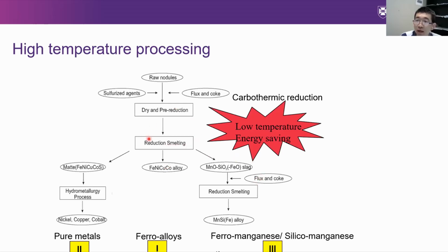This is a simplified flow sheet of nodules processing that we designed to produce three kinds of metal production. One is the ferroalloys, the ferro-nickel-copper-cobalt alloy. The second one is, instead of the ferroalloys, the pure metal, which is more favorable or accepted by the public. And then the residual manganese oxide-rich slags can be further reduced to produce either ferromanganese alloy or silico-manganese alloys.